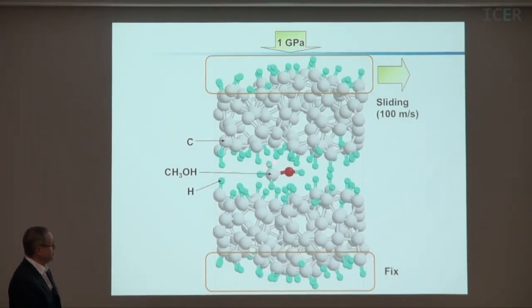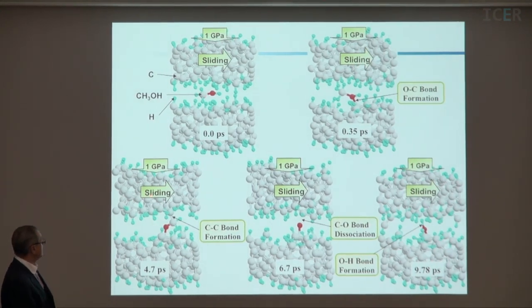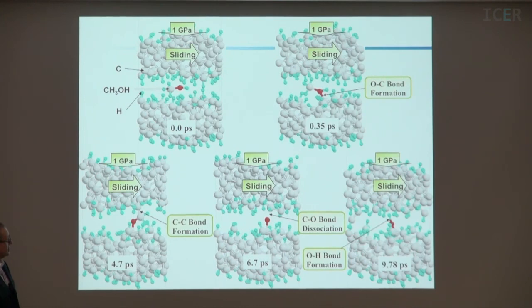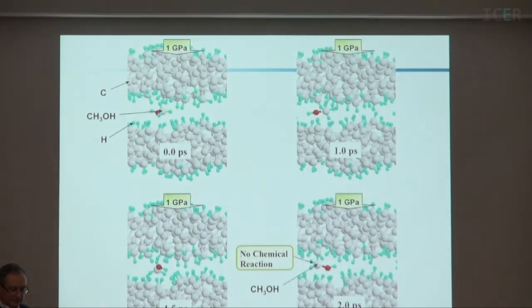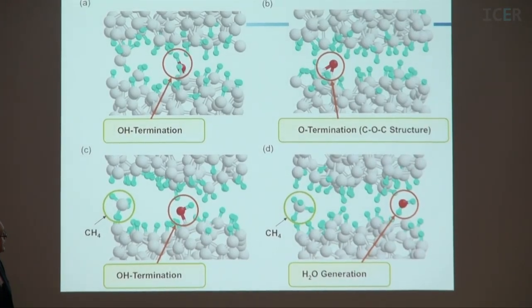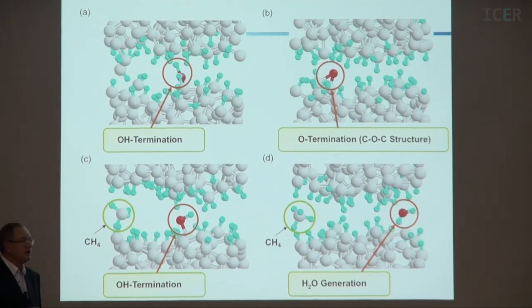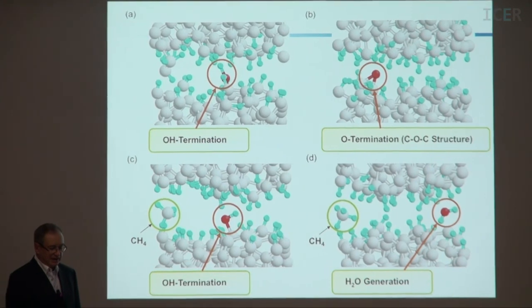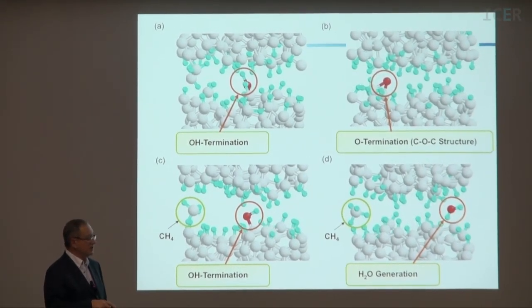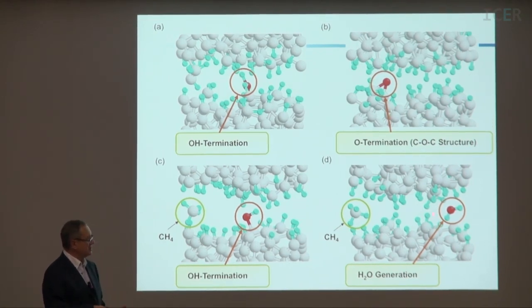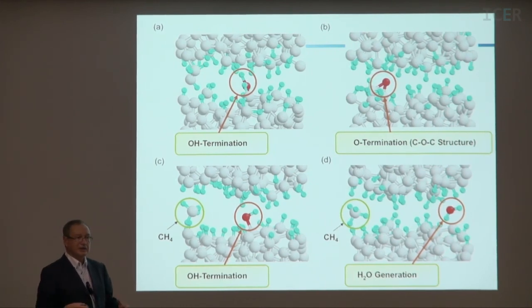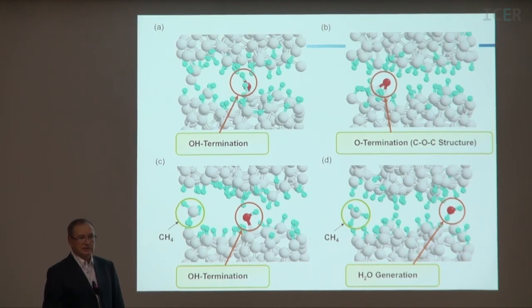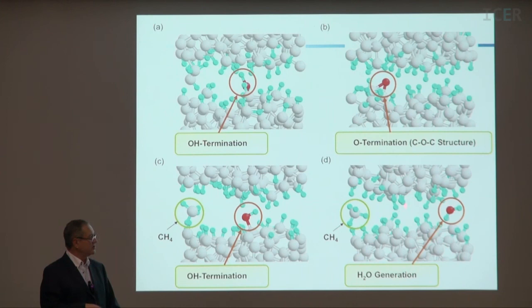Okay, so this is the original situation. And after friction, you can see here what happened. You have OH termination. Even you can produce water. So this is very interesting, but I have no time here to talk about that. We can lubricate with alcohol species, and these species transform into water in the contact. This morning I visited the tribology laboratory where they study hip joints and so on, and they look at the lubrication properties of water. Water is a good lubricant, but unfortunately it is not viscous. But here you can see that the water can be produced inside the contact area.